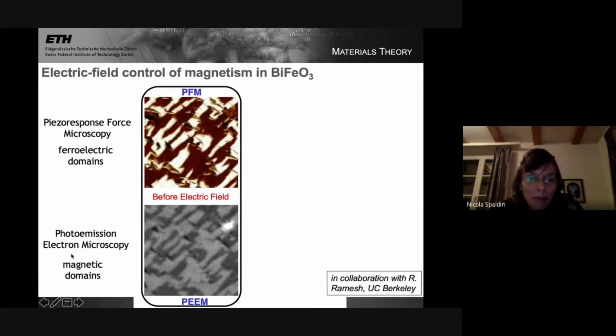Now, in the bottom half of the picture, this is the same region of space, but it's an image taken using a technique called photoemission electron microscopy, or PEEM. This technique is sensitive to the magnetic domains. The first thing I want you all to notice is that the pattern up here of the electric dipoles is very similar to the pattern down here of the magnetic dipoles. So there's this tuning fork. Somebody shout up if you can't see my mouse, because I'm pointing here. If you can't see it, then it probably makes no sense. But there's this tuning fork shape in the magnetic domains. We see it up here in the electric domains. This band here in the electric domains is down here in the magnetic domains, and so on. So we see that there's clearly a correlation between the electric and the magnetic domains.